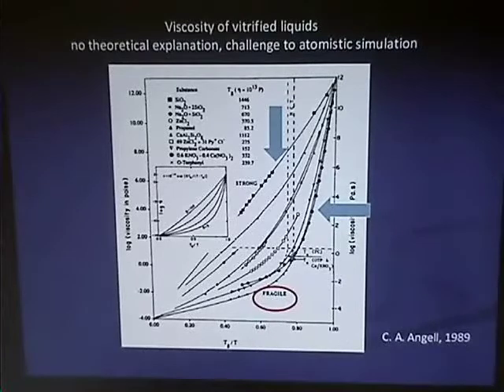What I'm going to show you doesn't assume there's a TG, it actually calculates TG, because it's a method to calculate viscosity. But you're both talking about TG, which is not this one. Well, TG is 10 to the 12 poise, just a convenient definition, no physics in it at all. So one must be careful about TG and TG. There are other ways of defining TG, but he's just completely arbitrarily said this is 10 to the 12 poise.